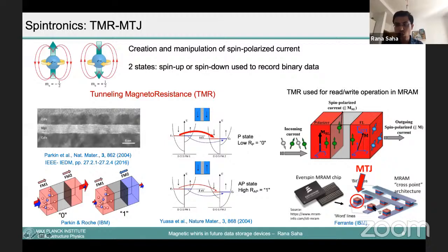So basically this is a solid state memory, unlike in a hard drive where the needle needs to move, which is mechanical, but it is much more reliable compared to hard disk memory. Now what happens here: if you put these small units in this cross array, you can pass a current through this word line and the current can exit through this bit line, and you can read by passing current whether these states are parallel or anti-parallel. When they are in a parallel state, you have a 0 state because there is a flow of current, and when there is an anti-parallel state, there's a high resistance state, no current can flow, and that will be state 1. In this way, one can read each of the magnetic bits using this magnetic tunnel junction.